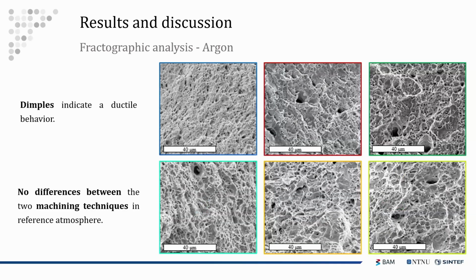Going to the images obtained with a higher magnification, we can see basically no difference between the tests conducted with solid and hollow specimens. So all of them manifest dimples, indicating a ductile behavior. And also there is no difference between drilled and reamed, as I mentioned before. And this is also reflected by the fractographic analysis, not only the stress strain curves. So basically we can conclude that the surface finishing has a strong impact when it comes to evaluating the influence of hydrogen on the mechanical properties, but it has no substantial impact in inert environments.